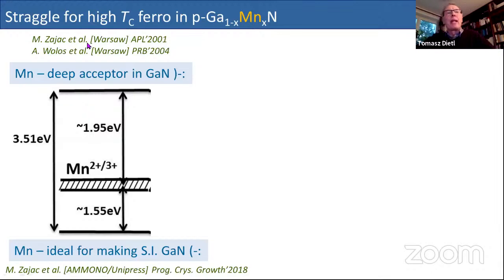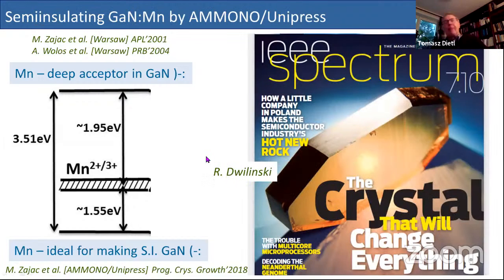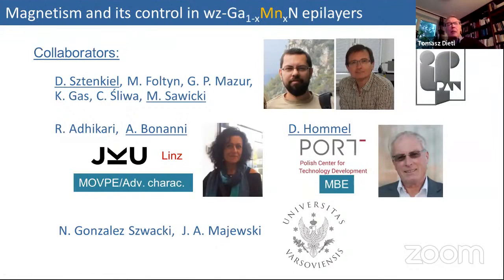And actually, Martin Zając, who was one of the discoverers of this high resistance of the material, started to work at the Ammono company. And Ammono now produces kilograms of gallium nitride with manganese. Maybe in your cars, you have diodes or power amplifiers which use gallium nitride and use this ability of gallium nitride with manganese to be semi-insulating, because this manganese level is very deep in the band gap. So this is one application of gallium nitride with manganese. But we are more interested in magnetism, and this is the subject of the seminar: controlled gallium manganese nitride.